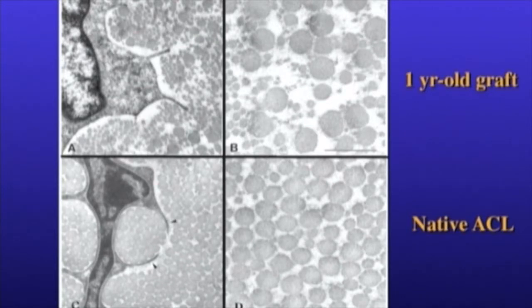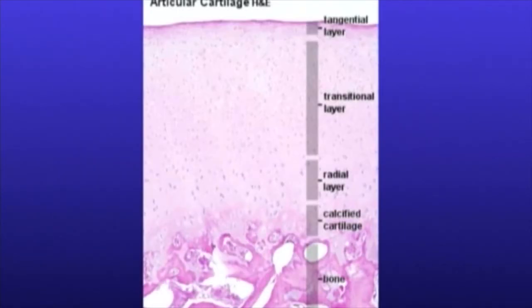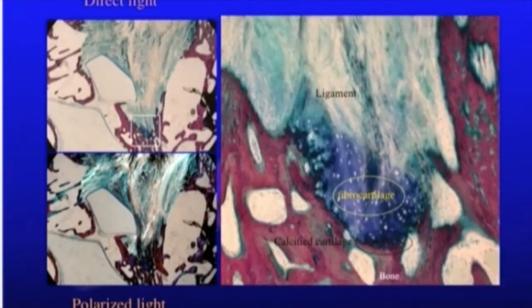And you notice there the big size of the fibers, but you also notice that there are not as many as in the native ACL after a year, which explains later on the gain in strength of the bioengineered ACL. But besides this, I must mention that big diameter collagen fibers are a sign of true regeneration. These are not a mass of little fibers that would be fragile, like in a wound that is freshly made.